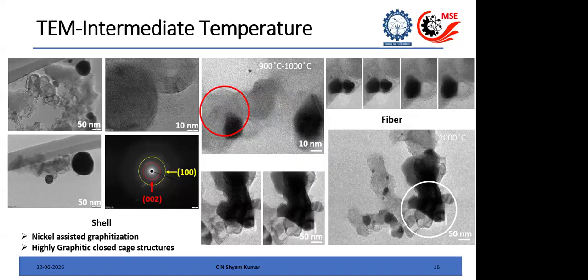So we know that the initial conversion to carbon is happening around 350 to 400 degrees Celsius. By that time, almost all the main volatiles are leaving the biomass. So the carbonization starts there. And you can continue like that until 1000 degrees Celsius without any catalyst, but you won't get highly graphitic carbon. If you want to improve the graphitic content, you need to use a catalyst. And when you use a catalyst, the graphitic carbon is basically precipitating out from the nickel. It is called the dissolution precipitation mechanism. So at normal condition at 1000 degrees Celsius, you have a moderately graphitic carbon, which means a mixture of sp2 and sp3. And when you use nickel at that temperature, you will have highly graphitic carbon.